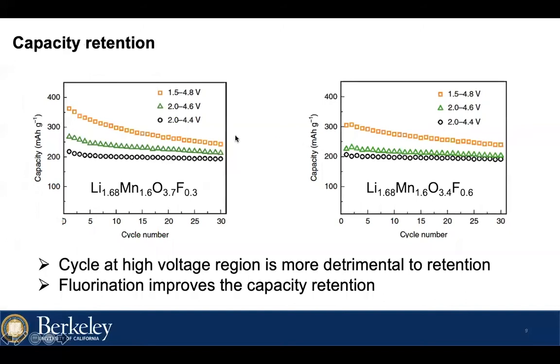And here shows the capacity retention of the two samples at different voltage windows. When this sample is cycled at 1.5 to 4.8 volts, although the initial capacity is high, the capacity drops relatively fast. This is due to the large amount of oxygen redox contribution. But when cycled within a small voltage window, it can achieve a capacity larger than 200 milliampere hour per gram, and it's still pretty stable. And with higher fluorination level, the capacity gets more stable even when charged to 4.8 volts. This is because the fluorine makes it rely less on the oxygen redox, and the fluorine can also suppress the irreversible oxygen loss.